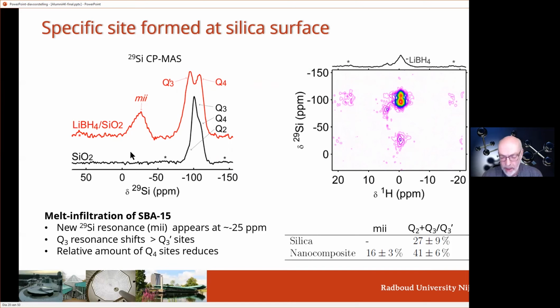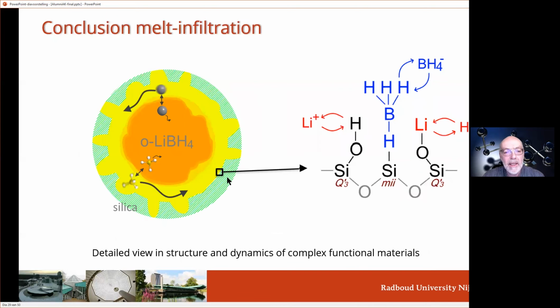And by bringing all this together, we could essentially postulate that at the pore wall, actually the lithium borohydride reacts with the silica. The surface of the silica gets reconstructed, and we form a completely new structure where we have a hydride, where essentially the BH4 is associated, and then the SiOHs, the silanols that are there, probably exchanged with lithium. And because you have such groups and the corrugation of the pores, that is probably the reason behind the fact that you have this very dynamic fraction, this liquid-like fraction in a solid material. But it's extremely useful because that can guide us to potential solid electrolytes that would have much fewer safety issues.